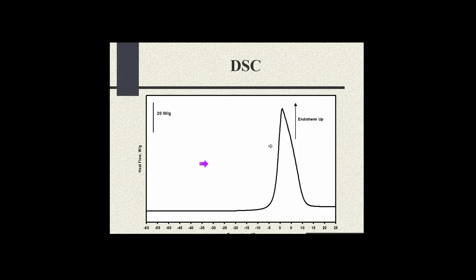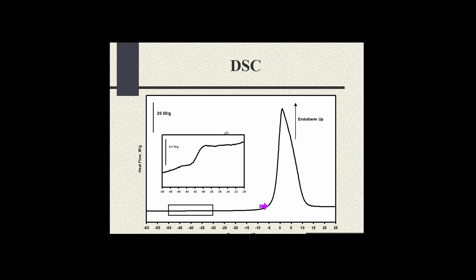This is a good example. I mean, glass transitions are very low energy events, so we do have to go looking for them. If we ran a DSC, looked at the warming curve, and took this for face value, we'd say, well, there's a eutectic melt here. Our product is safe all the way up to about negative 5. Well, the problem is, buried in the background, there's a very low energy glass transition. And if we miss that, you know, we're going to be in trouble. Our sample would collapse. We've got to keep this at much lower temperature. So this is where it tends to be a little bit misleading, unless you know what you're looking for.